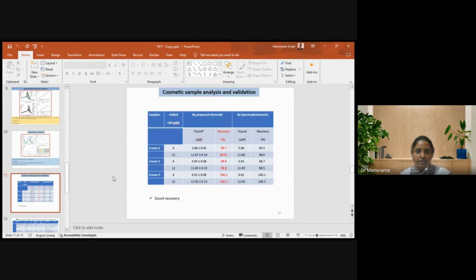Then we have done the cosmetic sample analysis. We have taken some cream from the local market and then used the standard addition method, and we found very good recovery results, with percentages from 99.7 to 100.1. We then validated this result with the spectrophotometric determination, and we found that there is good compatibility between the two methods.